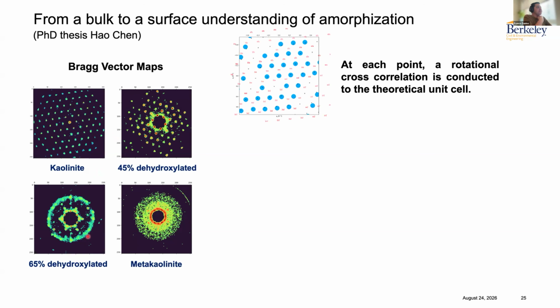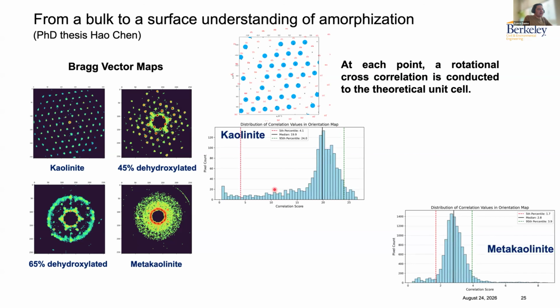Now, we can always index this, and what we do is that for each of these diffraction patterns, we try to index it to the known crystalline structure of kaolinite, and then we calculate a statistical cross-correlation parameter that tells us how similar the diffraction pattern is to the ideal crystalline structure. A higher correlation would mean that the material is very crystalline as compared to the structure file. A low correlation would mean that we don't have a lot of similarity between the electron diffraction pattern and the structure file. So, of course, you would imagine that kaolinite has a very high correlation because what we see experimentally is very similar to the structure, whereas for metakaolin, that correlation drops to about 2 to 4, where here we have around 20 to 25.